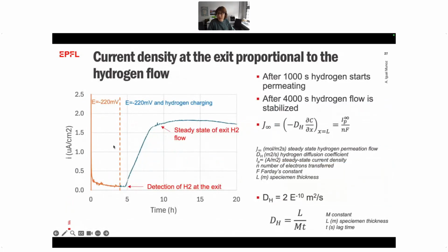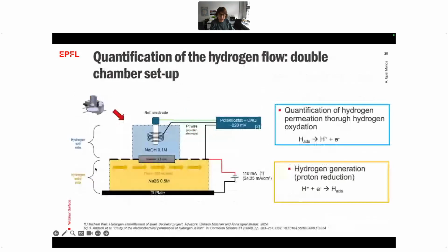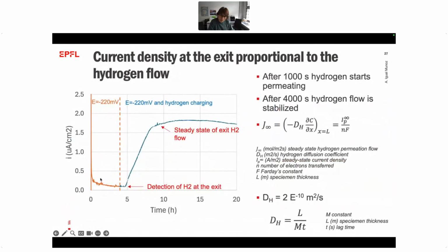So this is typically an example of how the quantification of this flow works. We impose certain conditions in the exit chamber, so we register the current. At the beginning, we passivate, and then we start charging the bottom part. Just from the current, and using Fick's law, we can directly extract the diffusion coefficient of hydrogen in my specific steel. This current is directly proportional to the hydrogen flow I'm going to have in my system.